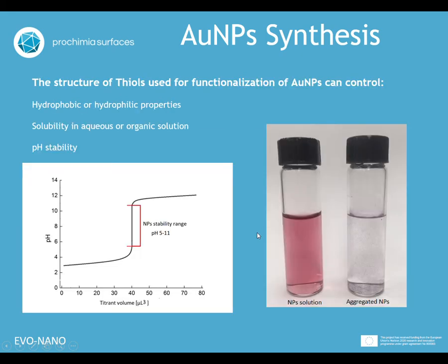In the case of gold nanoparticles, we can also smoothly and easily control their properties by appropriate functionalization of these nanoparticles. If the nanoparticles are functionalized with hydrophobic ligands, then hydrophobic nanoparticles will be obtained. Hydrophilic ligands will improve the solubility of these nanoparticles under aqueous conditions. Also important is that these nanoparticles are quite stable in a wide range of pH.